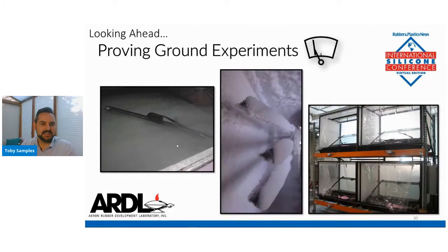Looking ahead, the next step is to simply mold the production blades. In our molding department, we were able to mold those blades and then apply them into these wiper test bucks, in which we would do dry and wet experiments. You get a qualitative wipe quality, and you can also do this winter slap test, in which, growing up in Ohio, we're often used to trying to shake that ice off your blades and to see if this additive affected the durability of those blades.